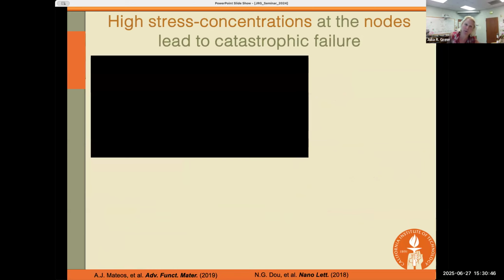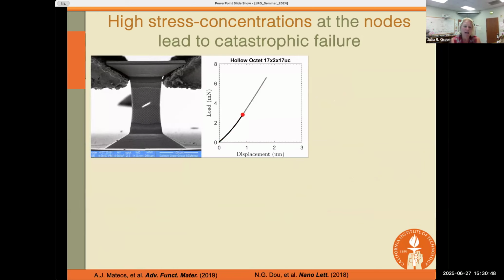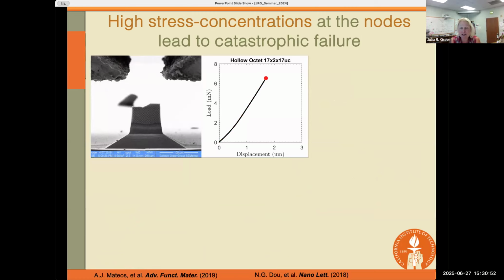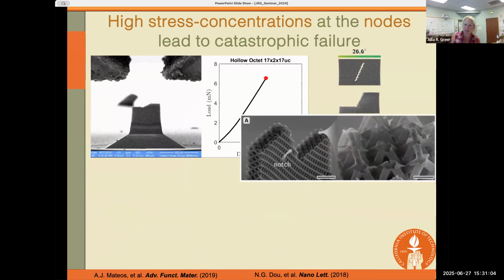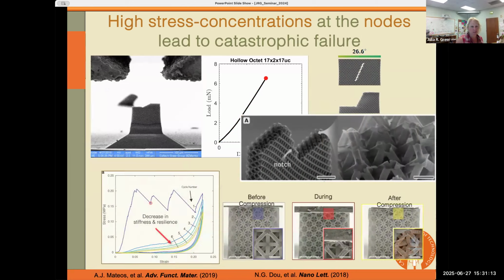So this is something that we're quite excited about. Spending just a little bit of time on tensile behavior, showing that, for example, the nodes in these nano-architected materials, one thing we really need to worry about is the nodes. Like we saw failure in the carbon materials, same thing is true for the tensile experiments. And so you can see that almost every time we performed a fracture experiment, it fails at these nodal planes, and that's where the damage is accumulating.